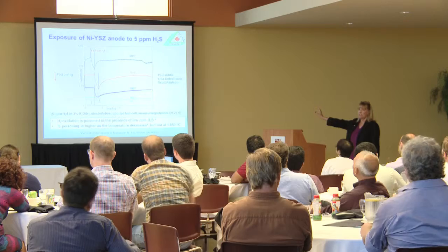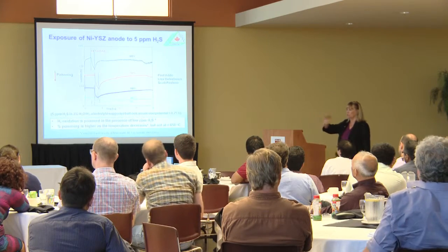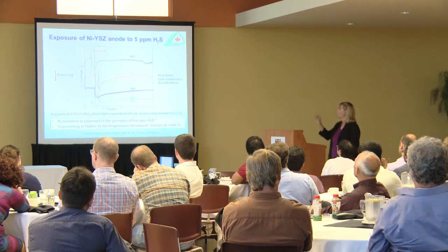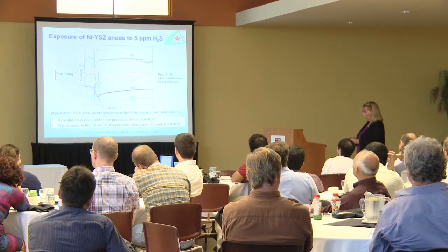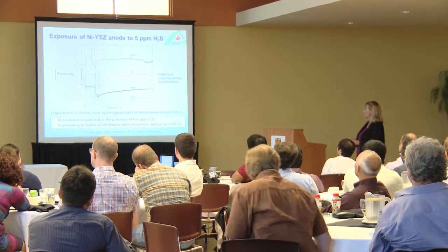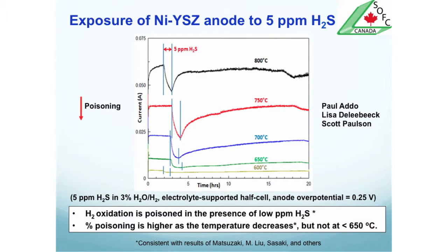So I'm going to start straight into some data because we had the literature issues already covered a little bit by Kunal. This is a plot of current as a function of time as you run humidified hydrogen through the cell, and then bring in just 5 ppm H2S. You can see that the current drops. When you remove the H2S, it goes back up again, but slowly, it slowly recovers.